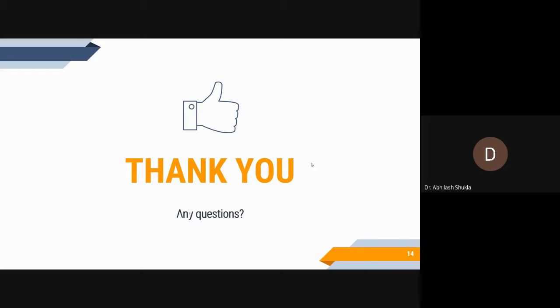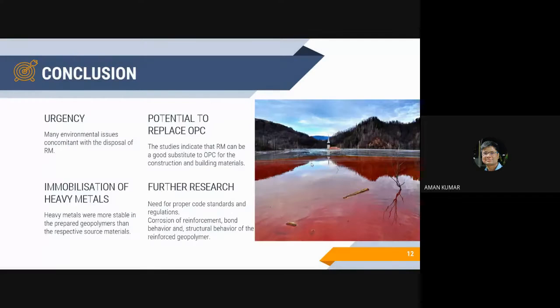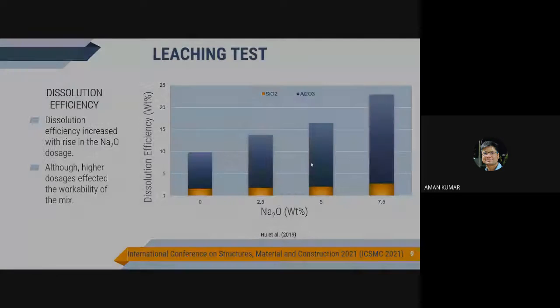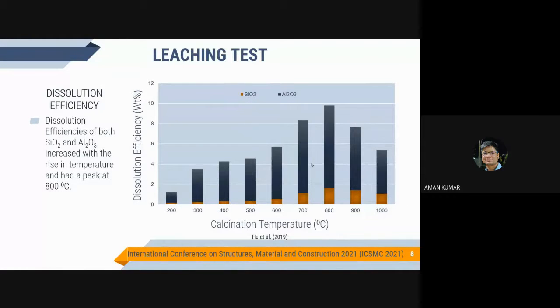I have one question from my side. How does red mud influence the hydration chemistry in cement part? So, in contrast to the formation of bonds in the ordinary Portland cement, the major formation that takes place there is the CSH gel formation. But here, rather, aluminum and silicate together form a chain of molecules, and here the major gel is formed by both alumina and silica. That is why the researchers have focused more upon the leaching test of these two compounds.